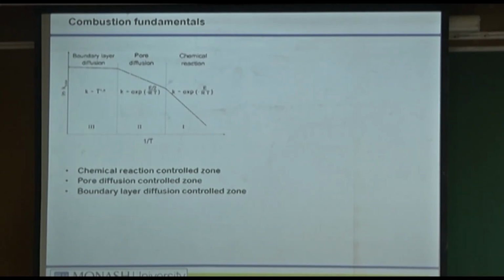So what they do is take a piece of coal, or a piece of char rather, a certain amount of char, hit it with oxygen, and measure the oxygen content at the outlet, so that you know how much oxygen you have given, how much is coming out, so how much oxygen has been consumed, and then you plot it. Yes, that's right, or it can be done in a flat flame burner as well.